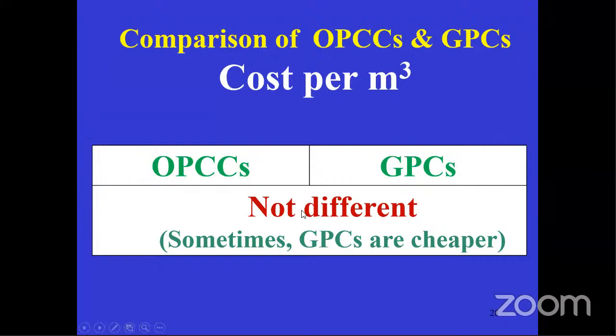And I'm sorry, here I'm using the word geopolymer, but according to him, he always tells me, don't use the word geopolymer, use the word alkali activation. As soon as you increase the amount of fly ash more than 80%, it tends to be a geopolymer. Okay. And if you use less than that, it tends to be not at all geopolymer, but we don't have an alternative. It is a glamour word. We are using geopolymer wrongly.